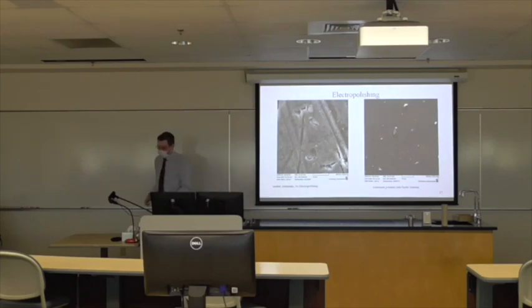In addition to that, the 80 Celsius with a basic solution, while still better than using perchloric acid, for example, isn't the most ideal situation for safety concerns as well as energy use and things of that nature. So we did recognize that this worked, but we wanted something even better than that. So we moved into the deep eutectic solvents.